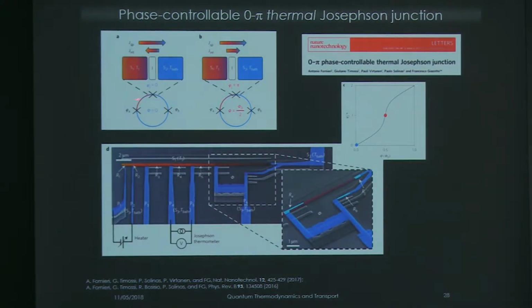The structure here can be realized by implementing a sort of pseudo radio frequency SQUID. So a SQUID where we have three different junctions, and taking into account that if we make the junction of interest, that is the phi j, with resistance much larger than the other, so that each critical current dominates the full phase landscape of this device, all the phase drop will always fall at this junction here.